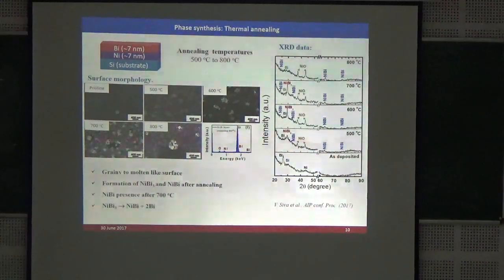So this is the XRD data. As deposited films show the presence of nickel, silicon, and bismuth. And after annealing, we see presence of both stable phases, NiBi and NiBi3. And these phases are stable until a temperature of 700 degrees centigrade. After that temperature, like I was showing from the phase diagram, this NiBi3 decomposes into NiBi and bismuth.